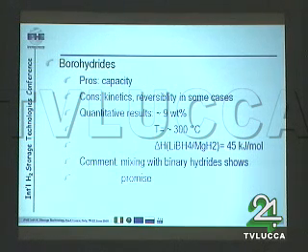Borohydrides. Pros are capacity; cons, kinetics, reversibility in some cases. Quantitative results good, about 9% in weight. Temperature rather high, 300 degrees centigrade. Enthalpies 45 kilojoule per mole. Mixing with binary hydride shows promise.